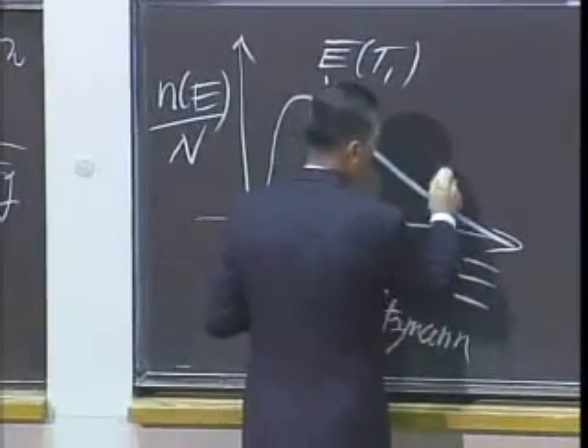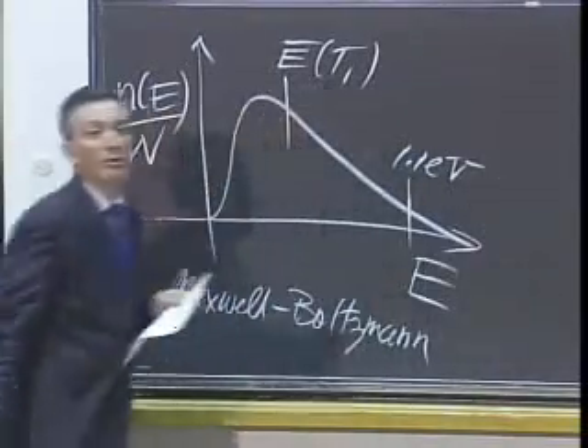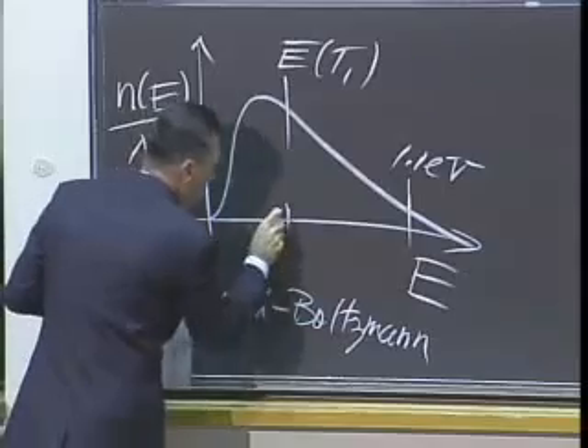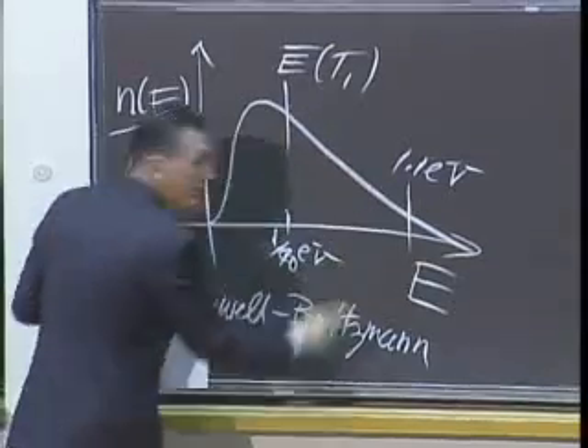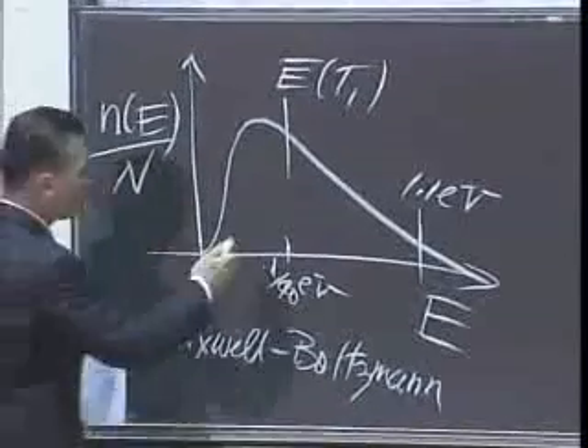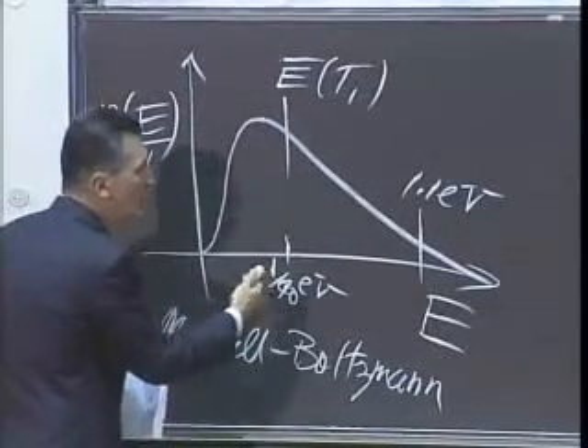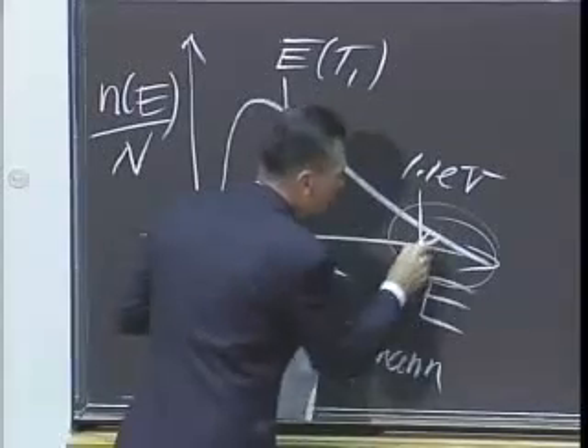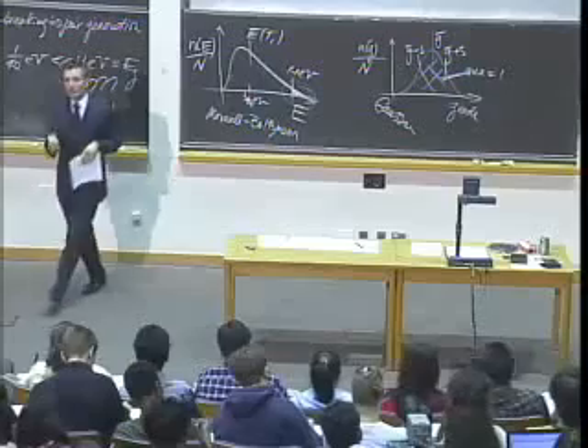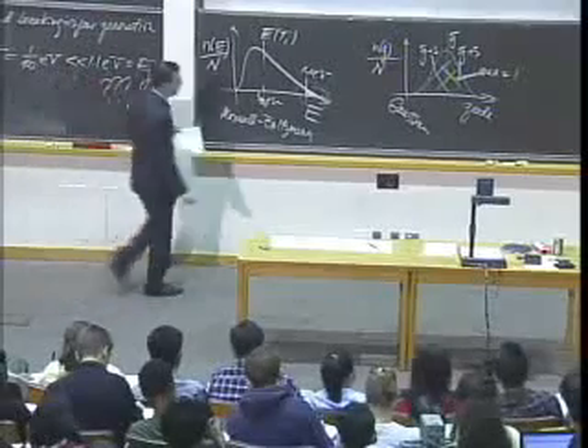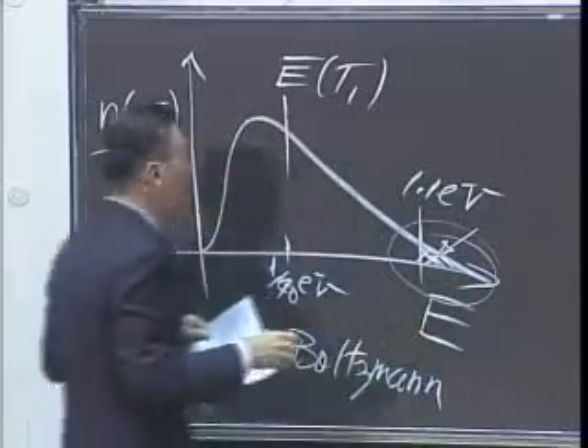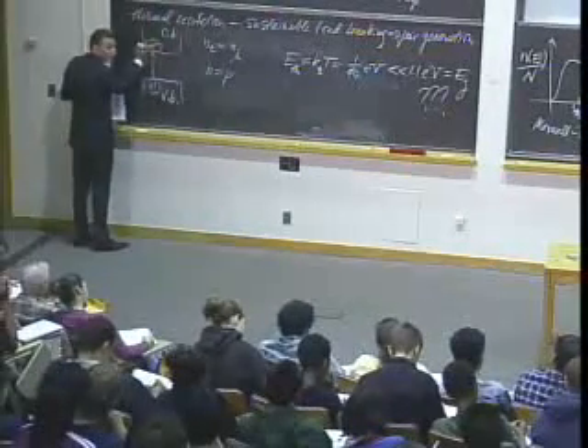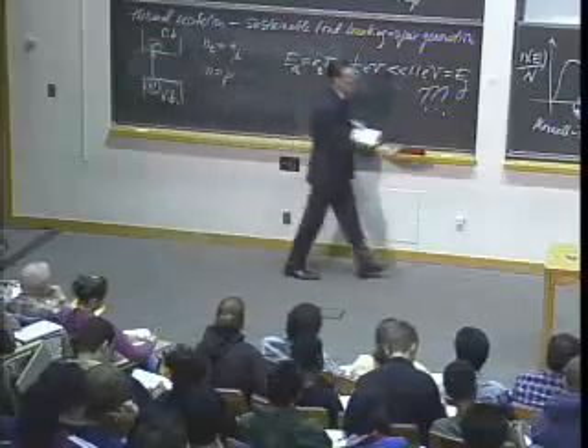And what I want to do is focus down here. Suppose up here this is 1.1 eV. Well, the average value is here, and I said that this was 1/40th of an electron volt. That's not the problem. The good news is that there is some tiny fraction of the distribution that has energy above 1.1 eV. So if I knew what that fraction was, then I could guess how much I could expect in the way of promotion here. You can see it's non-zero. It's not a sharp cutoff.